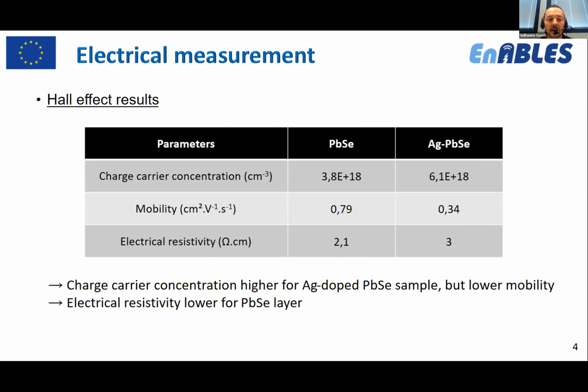As you can see, the charge carrier concentration obtained was higher for silver doped PbSe samples. So it's quite logical due to the silver doping. But we measured a lower mobility. And so the electrical resistivity was lower for the PbSe layer compared to the samples with silver doping.